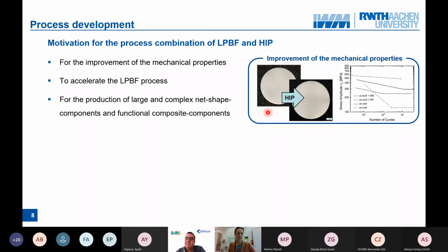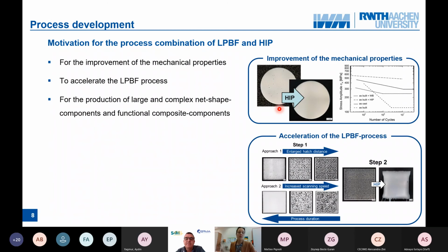And by having the possibility to reliably close porosity by hot isostatic pressing, maybe the relative density before the HIP process does not need to be 99.9%, because such a high quality requires a very long process time. Therefore the second motivation for the process combination of LPBF and HIP is the acceleration of the LPBF process and the approach to build samples with more porosity but faster, and then HIP them afterwards and have fully dense samples after the HIP process.